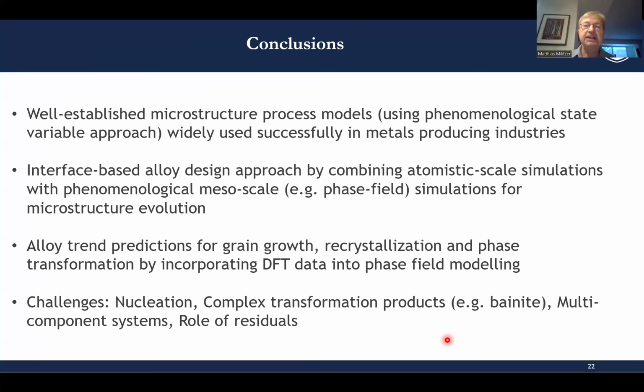We propose here an interface-based alloy design approach where we combine atomistic scale simulation with phenomenological mesoscale simulations, in particular phase field, which is also a powerful methodology to deal with complex morphologies in the microstructure, like in bainite. And then we can make alloy trend prediction for grain growth, recrystallization, and phase transformation.